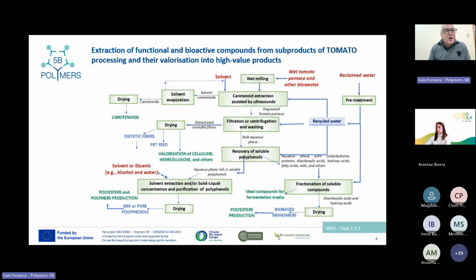So basically, the extraction of tomato pomace is what we started working on at the beginning. We start by separating the skin from the seeds of the tomato and go directly to produce dicarboxylic acid and hydroxy acid that mimic the coating plastic of tomato, and then try to produce bio-based monomers and polyesters with this direct strategy.